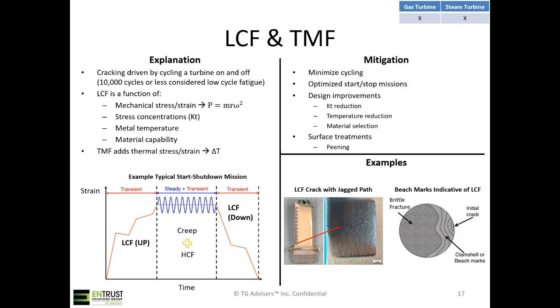So LCF and thermal mechanical fatigue is cracking that is driven by cycling a turbine on and off, or by aggressive transients. Typically 10,000 cycles or less is considered to be low cycle fatigue when you look at your S-N diagrams. LCF is driven by mechanical stress and strain, as you know, and you get tons of that from your pull load. Any sort of stress concentrations, a lot of times if you have root fillets or tight radii, those are the areas most probable to crack.